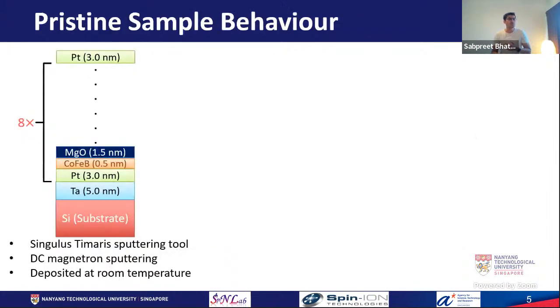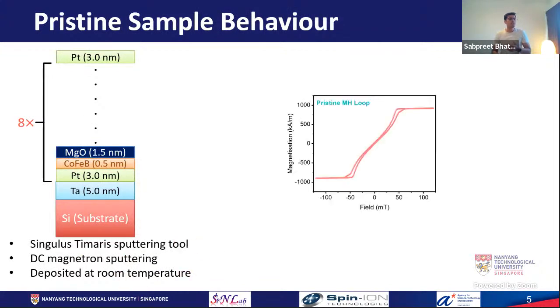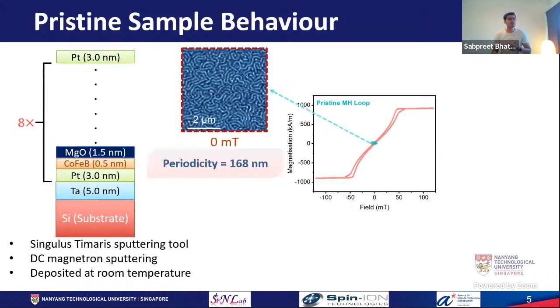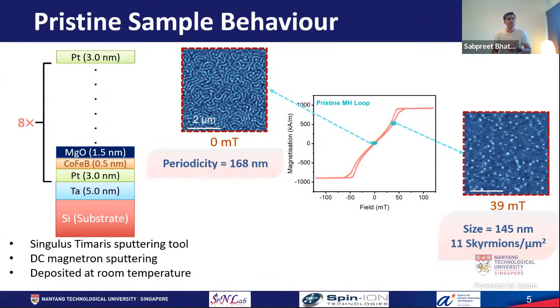Now, this study has been carried out on a cobalt iron boron 8 repetition sample, which was deposited using a Singulus Timaris tool. Here I show the hysteresis curve of the pristine sample, and this sample shows a very dense state at zero field with a periodicity of 168 nanometer. On increasing the magnetic field of imaging, we observe a sparse skyrmion state around 39 millitesla with a size of around 145 nanometer with a skyrmion density of 11 skyrmions per square micrometer only.